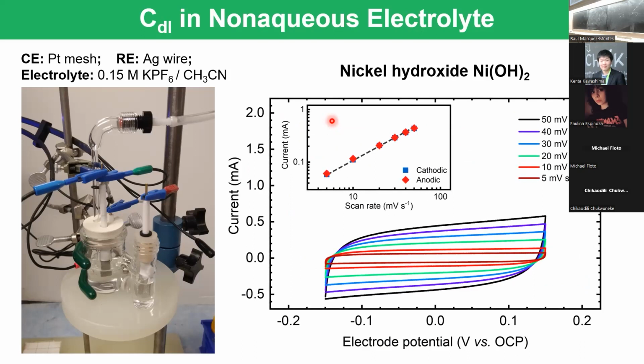I told you one difference is the current. What else? Smaller scan rate. Smaller scan rates, right? We were able only to get this behavior from 5 to 50. We tried, my undergrads know this, we tried faster scan rates and the result was worse. So that means that probably the material is not conductive. So at first I was like, okay, I will just pick these values. And then my friend was like, oh, the reason why you're having trouble is because it's not conductive.